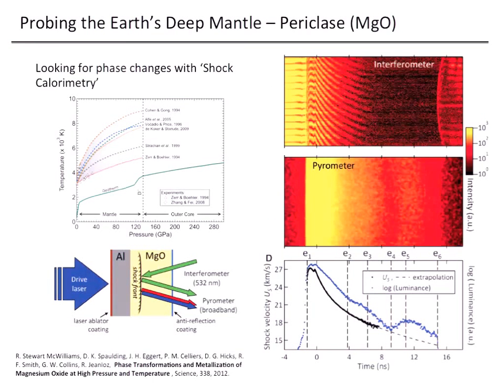So going back to the case of MgO, one of my first thesis projects was to develop an optical pyrometry system at the Janus facility so that we could measure temperatures to go along with the kinematic shock variables that are traditionally measured, and to attack problems like this, to look at where materials melt at multi-megabar pressures.